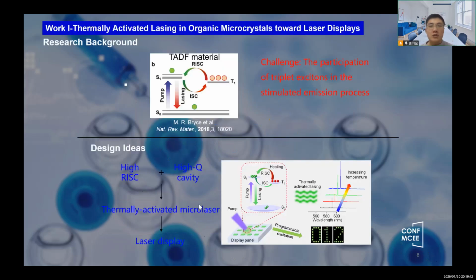First, let me introduce the first work, thermally activated lasing in organic microcrystals toward laser displays. The unique energy level structure in thermally activated delayed fluorescence materials allows for the utilization of triplet excitons through the reverse intersystem crossing process, potentially solving the problem of triplet exciton losses in micro and nano lasers. However, experimental evidence for the feasibility of this concept is still lacking.